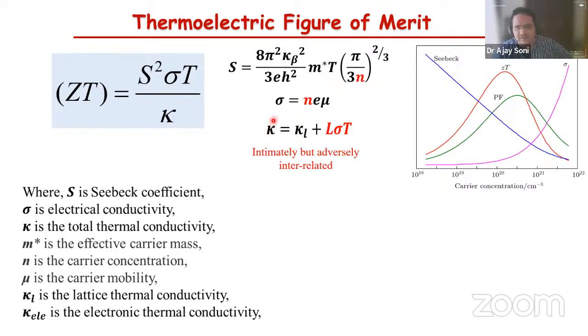And the thermal conductivity has two different parts. One part depends on the lattice, and the other part depends on the charge carriers, the electrical part. So you can see that if you have more charge carriers, your thermoelectric power will be low, while your electrical conductivity will be high. And if you have more charge carriers, the electronic part of the thermal conductivity will be high. So more charge carriers are not good for optimization of this particular equation. You need a material with a better optimization of the charge carriers.